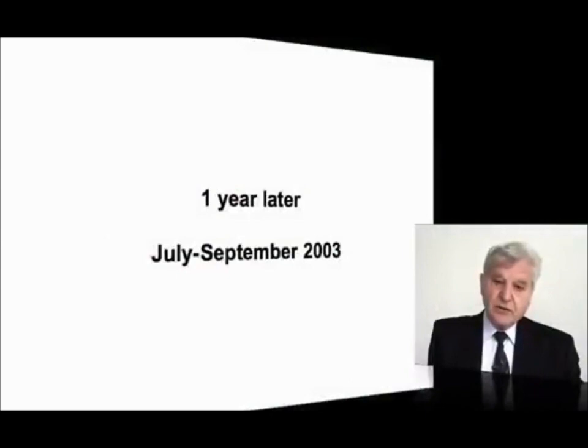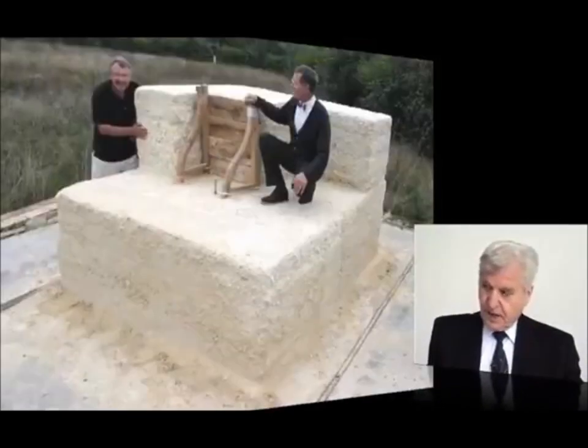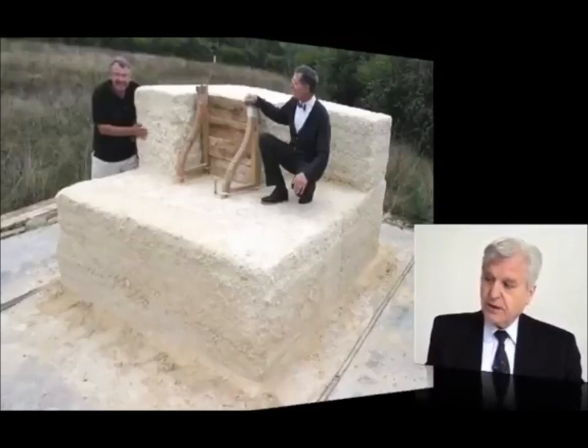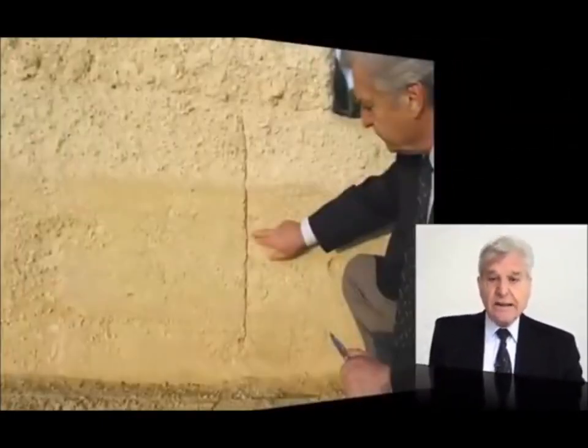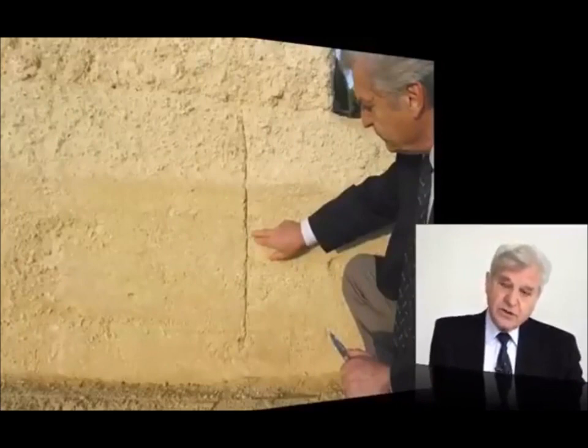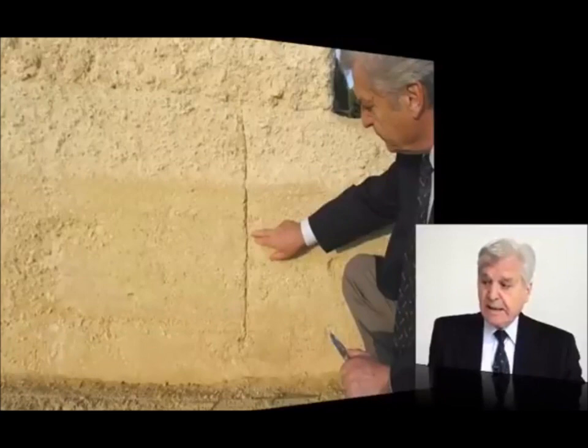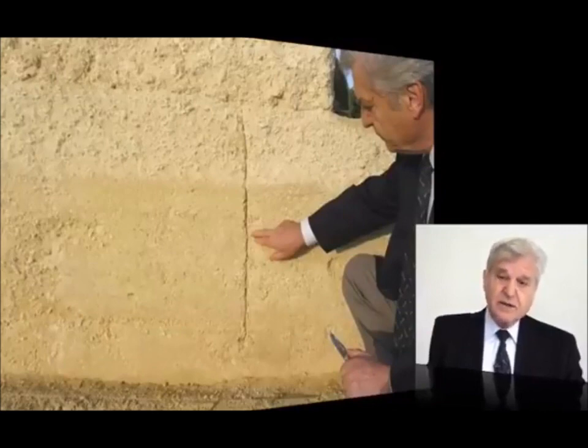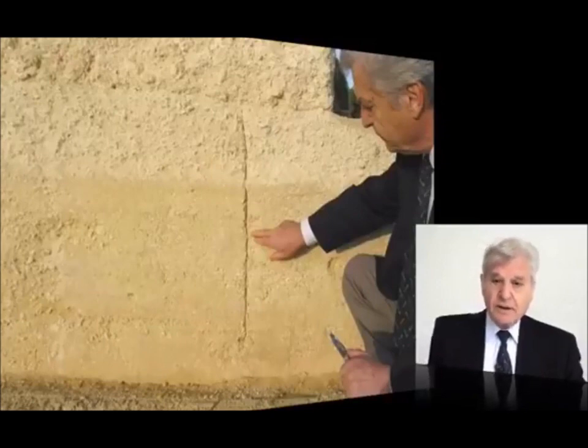We looked at the stones 1 year later. This is how it looked when we reopened the molds and the shelters. You remember in the video we had been claiming that we cannot see the joints between the stones. Well, 1 year later we have the joints, and this is obvious because each block during hardening is shrinking. The shrinkage is very small, but it is sufficient to produce a joint between the blocks, and each joint in fact is the mirror of the other. They are perfect and they are exactly the same shape as what we see on the pyramid site.